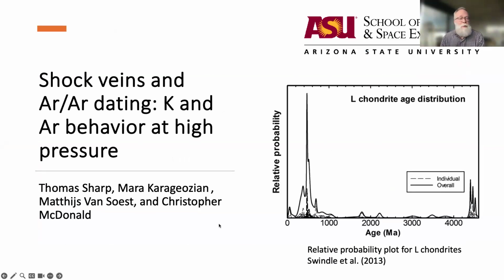I'm going to answer John Fink's question. Can these be replicated in impact cratering experiments? Yes and no. The majority of impact experiments that are done, these shock recovery experiments, you put the sample into a stainless steel container and you shock it and you recover it. It's a great way to shock a material and recover it, but what it does is it gives you high pressure by shock reverberation.